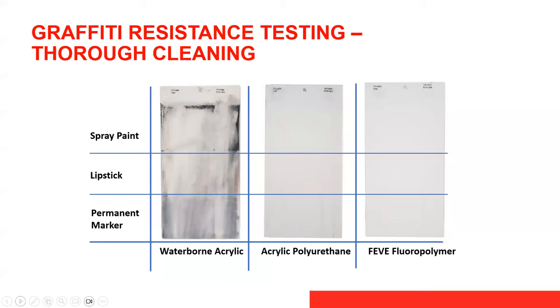Again, a waterborne acrylic is a one component. They tend to be water-based. They have a little bit of a softer film than a two-component chemically cross-linked top coat like a polyurethane or a fluoropolymer. The polyurethane did well. It's hard to see probably on your screen. There's a little bit of shadowing, especially with the permanent marker. But overall, the majority of it was removed, and it looks pretty good. And then the fluoropolymer, really, you can see almost no detrimental effects that are left after the thorough cleaning.